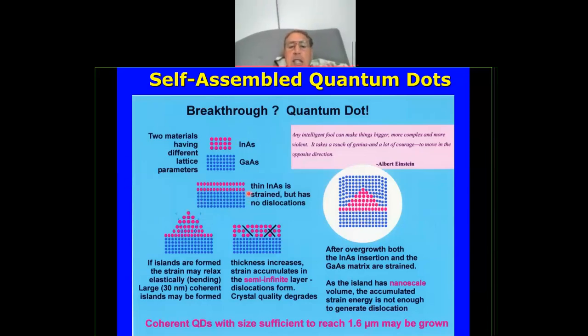So first, this layer is very, very strained, but when you go above a certain thickness, that strain becomes an island. This is like a droplet of water on glass. If you put water on glass, first it's a thin film, and if you put more, then you start having droplets because the surface tension between the water and the glass is different. So this is what we have for quantum dots by this self-assembly technique.